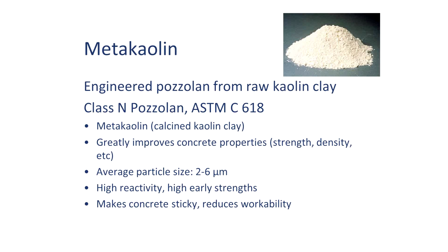It's an engineered pozzolan. They take raw kaolin clay. Most of it's mined also in Georgia, ironically, right next to where VCAS is made. And it's calcined, which means it is heated at a very controlled temperature for a very controlled amount of time, and it chemically changes it. So metakaolin: meta is Greek for change, and kaolin is a type of clay. So they changed the clay. You'd never ever put kaolin clay in concrete. It would weaken your concrete. But when you use calcined clay, it's chemically changed, it's now chemically reactive.